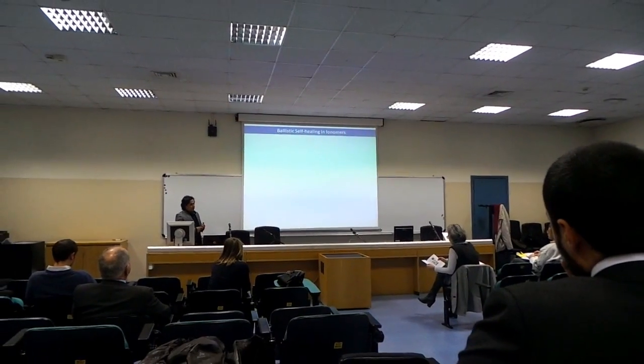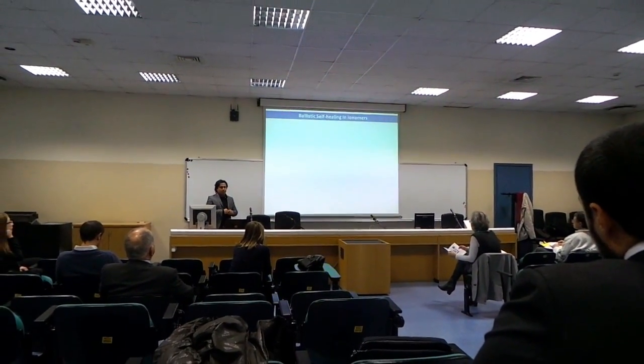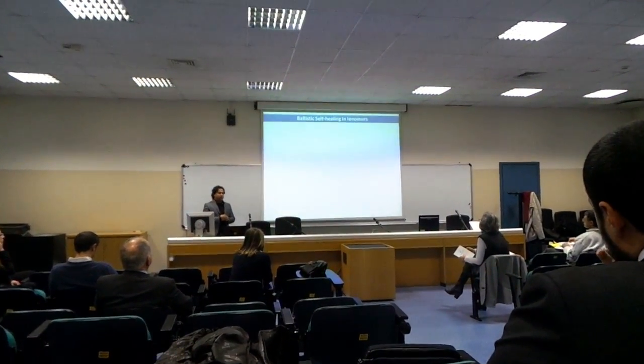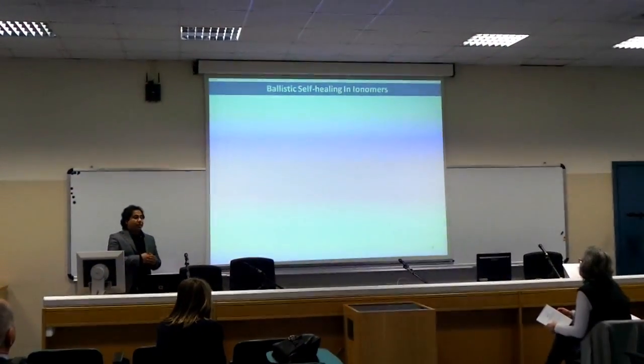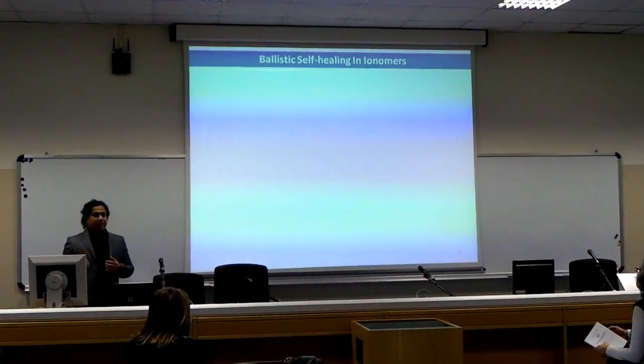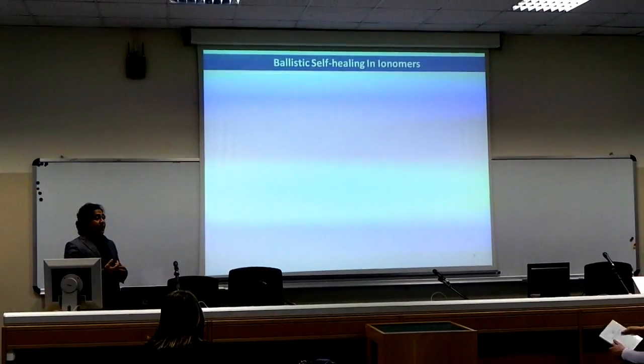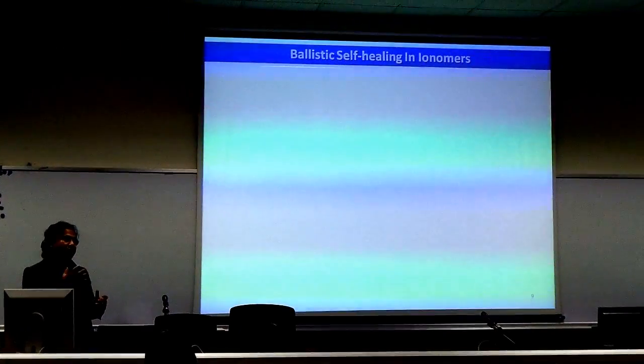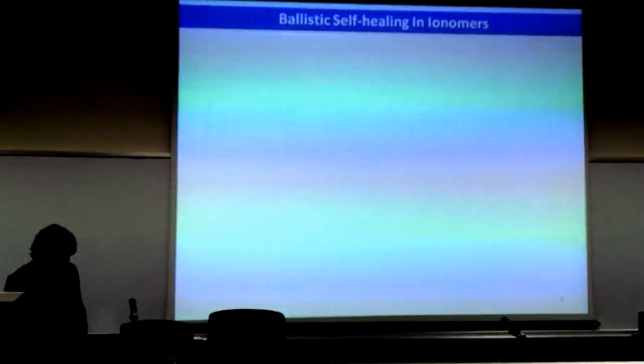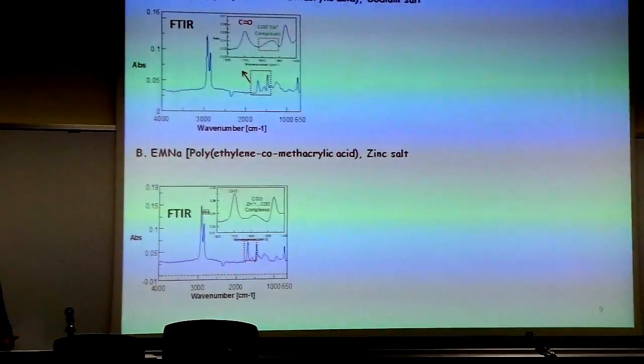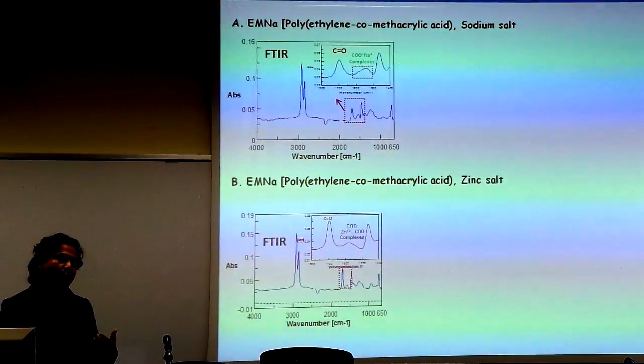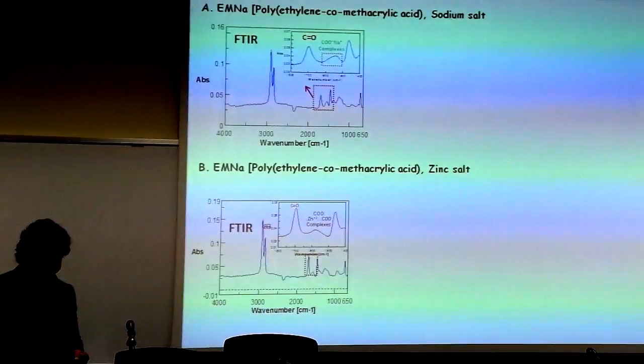At the beginning, I started studying the ballistic self-healing in ionomers. I should mention here that ionomers are random copolymers that contain both polyethylene and methacrylic acid content, where the methacrylic acid content is usually 15 weight %, and this acid is partially neutralized by metal ions like sodium, potassium, or quaternary ammonium ions. So I studied 2 different ionomers, polyethylene methacrylic acid containing both sodium ion and zinc ion.